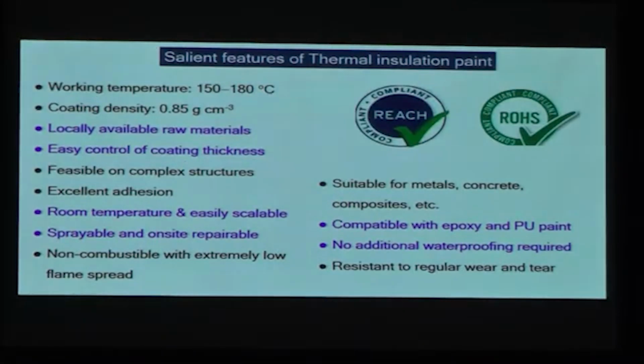So the salient features of the thermal insulation paint, in brief: this paint is suitable for applications providing thermal insulation against hot air for temperatures up to 150 to 180 degrees centigrade. The density of the coating is very low, about 0.85 gram per cc. The paint is developed using locally available raw materials. The deposition technique is also very simple and doesn't need any sophisticated machinery. Hence, it can be easily adopted into the industries.